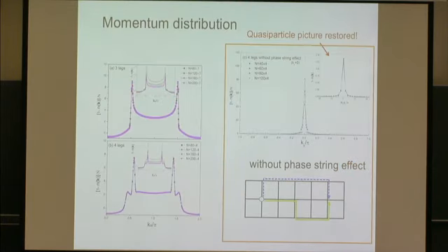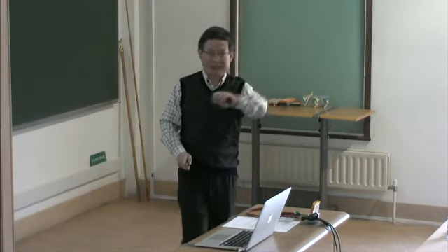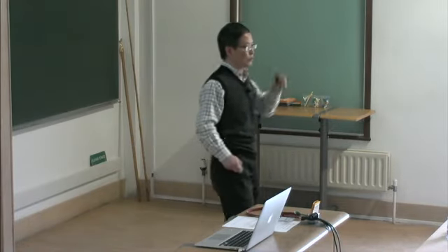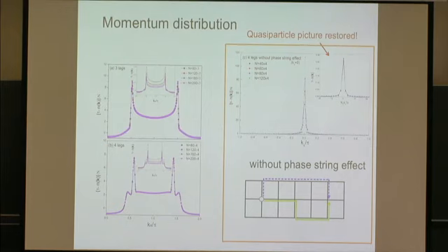You find that once you turn off this sign, the momentum distribution shows a very sharp delta peak at K0. It tells you this doped hole really becomes mobile, becomes a Bloch state with reduced quasi-particle weight. This is because there is only one hole, so it's not a Fermi sea; there's no Fermi surface. It's just one particle here. But once you turn on the sign structure in the t-J model, you see this distribution has very strange behavior. The summation gives you one hole, because the sum rule gives one hole, but you see this very rich feature.